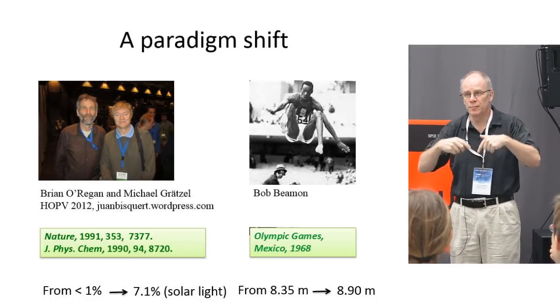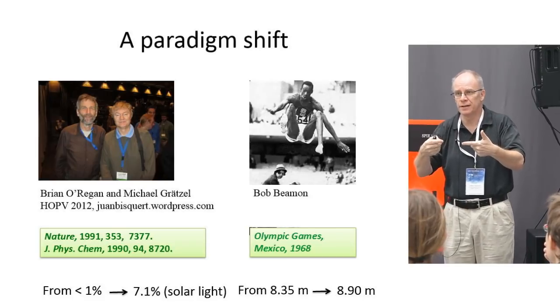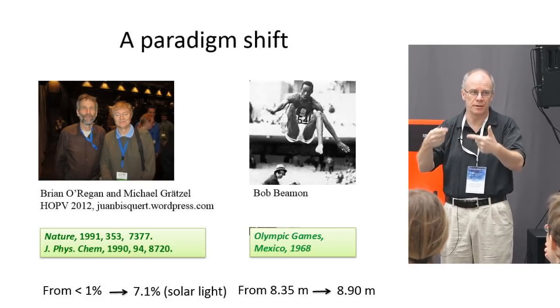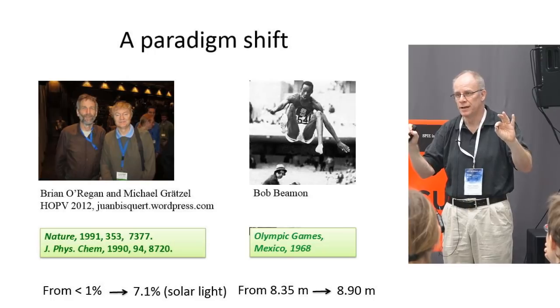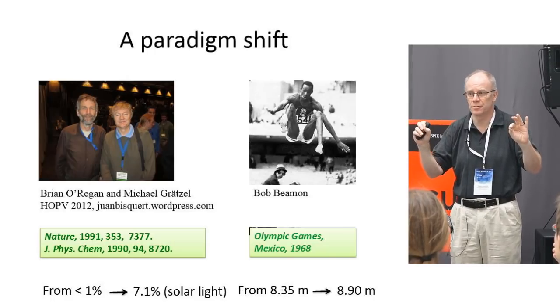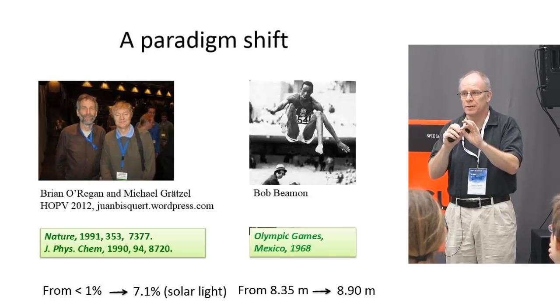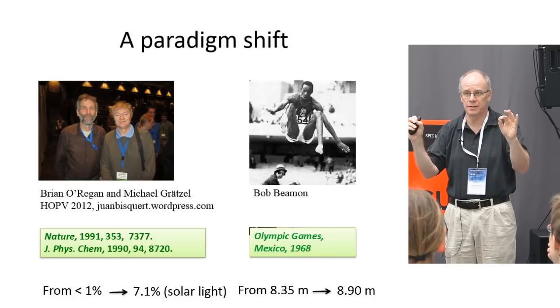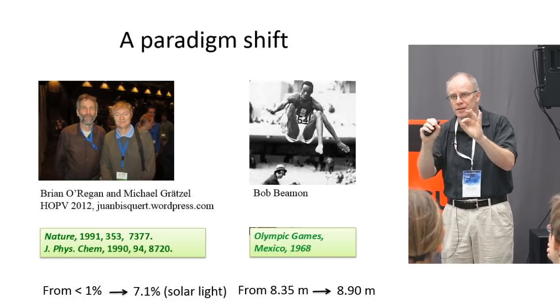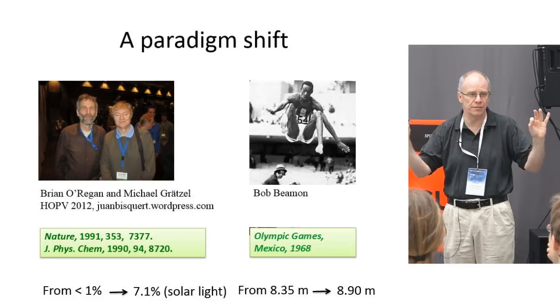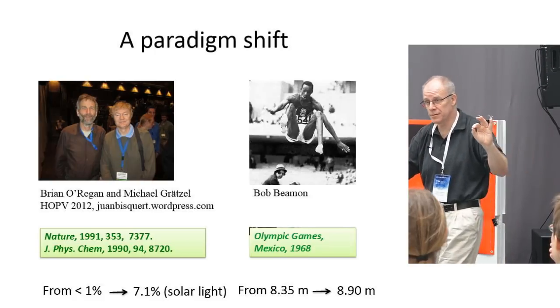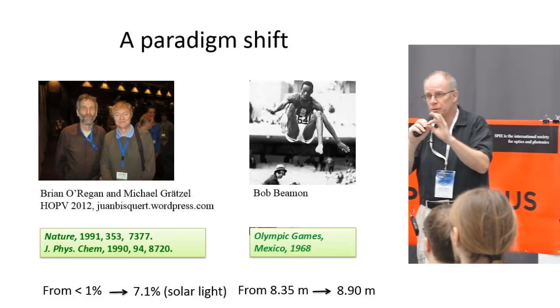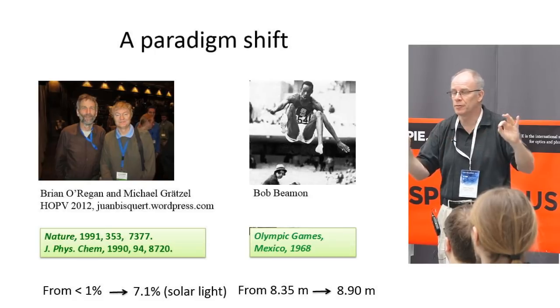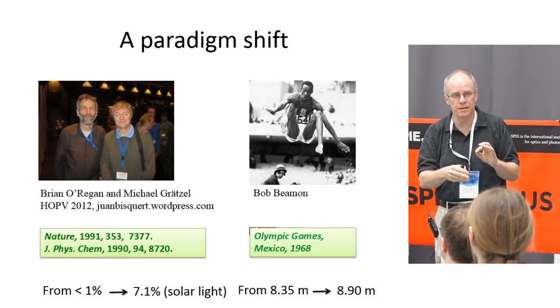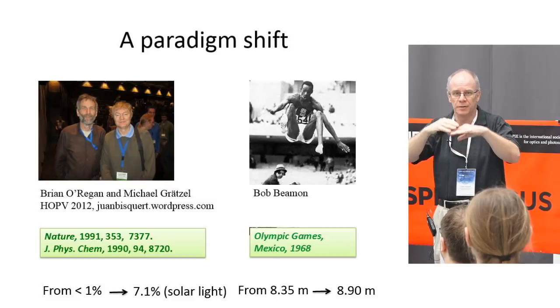But if you now use one molecular layer of dye, the probability to absorb light by one monolayer of dye is very low, maximum 1–2%. So visibly it will look like a window. It's completely transparent. Maybe a faint color of this monolayer of dye. So it's not enough to absorb a lot of light. And people were sort of focused, well, we can only have one monolayer to make this injection efficient. If we have multi-layers, we will not have injection.